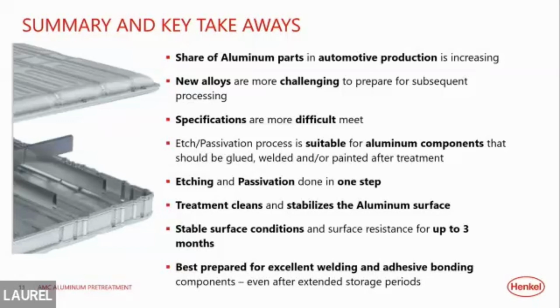with the new alloys. The etch passivation process works very nicely for aluminum components that are going to be glued, welded, or painted after treatment. It stabilizes the surface. As I said, the one thing, if I leave you with good to know, is that that aluminum oxide coating, as soon as you remove it, it will come right back if you do not stabilize that surface immediately. So this product, Bonderite MNT 2040 R2, is also used on aluminum wheel lines